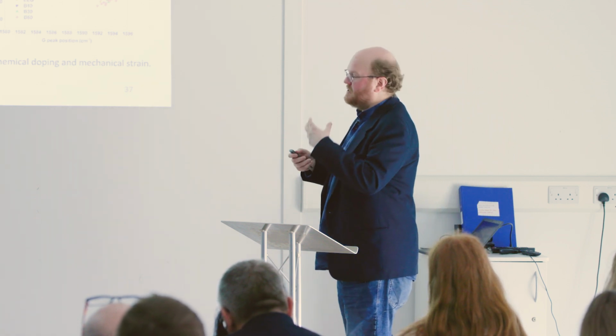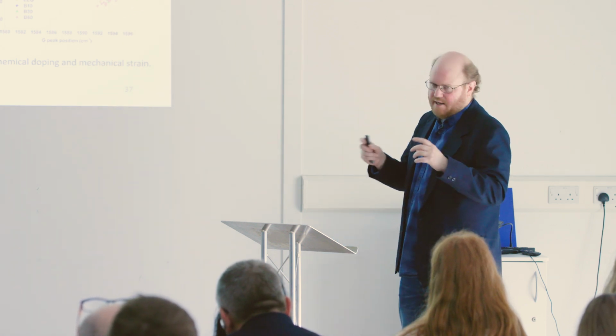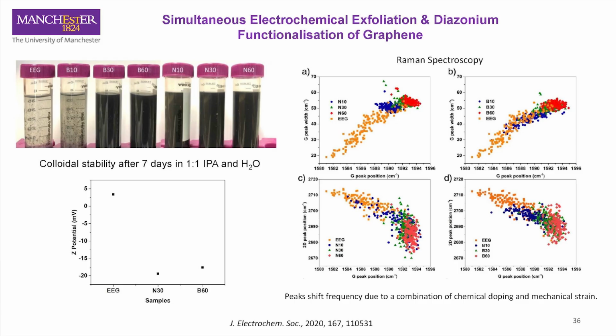We see that the peaks of graphene are shifted, both by a combination of mechanical strain, because you've got this functional group on there, but also doping, where it's either electron withdrawing or electron donating from the surface. So that gives us this spread where we can basically, using Raman, determine how functionalized our material is, combine that with how stable it is in solution, and then what kind of electrochemical performance we expect to see from it.